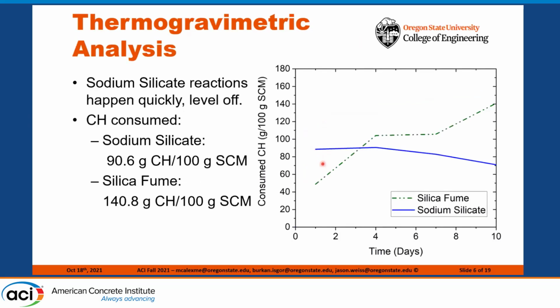The TGA graph of sodium silicate also shows a very quick reaction, with the majority of the CH consumption happening within the first day, where the silica fume is seen to continuously increase its CH consumption over the course of 10 days. Sodium silicate consumes about 91 grams CH per 100 grams SCM, and silica fume consumes about 141.